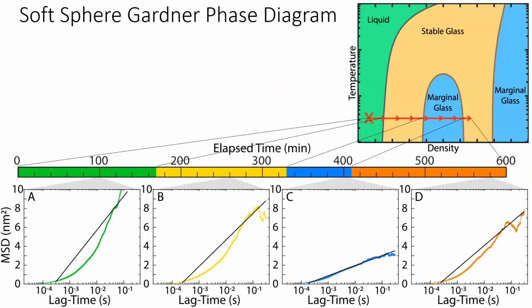And here we can compare this to a predicted phase diagram of soft colloidal glasses, where at a fixed temperature, as we increase the density, we should be liquid and then a stable glass, and then through this marginal glass, and actually back into the stable glass. And what we see as a function of time, I'm just showing the log linear scale, is non-logarithmic, logarithmic, and then non-logarithmic again. So this, I would argue, is direct experimental evidence of this Gardner phase.